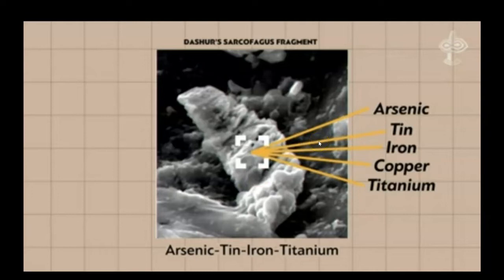And here is another beautiful scanning electron microscopy image showing a metal microparticle found from a stone cut in Dashur that is a fused particle of copper, arsenic, some tin from the blade, and iron and titanium from the abrasive slurry. And sure, the cutting process generated heat, which is why they constantly introduced water as shown in the previous slide. And these scanning electron microscopy images are absolutely spectacular because we can actually see a tiny glimpse of the miraculous, brilliant chemistry and metallurgy of the ancient Egyptians. End story, and I rest my case.